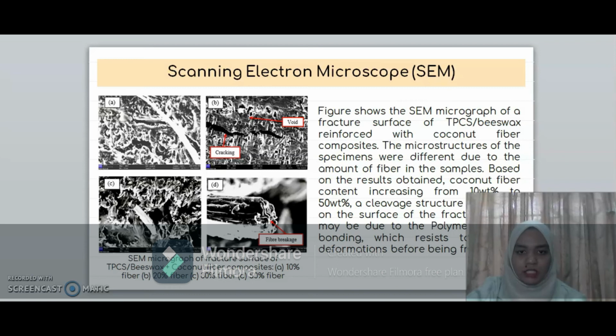Next, we move to scanning electron microscope, SEM. There are defects such as cracks, voids, and fiber breakage. The figures show the SEM micrograph of the fracture surface of TPCS beeswax reinforced with coconut fiber composite. The microstructure of the specimens was different due to the amount of fiber in the sample.